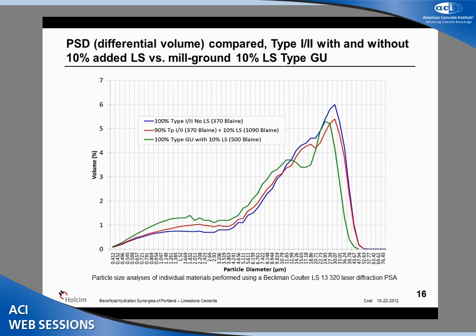We then took the different materials that we had been using in the laboratory, both the separately proportioned materials as well as the Portland limestone cement ground in the mill, and we did a particle size distribution analysis of these materials and actually proportioned in an Excel spreadsheet what they would be for the separate components that we had batched in the laboratory. The ordinary Portland cement is in blue. This is about 76 microns. This is about half a micron in here to give you an idea of where you are on the chart.